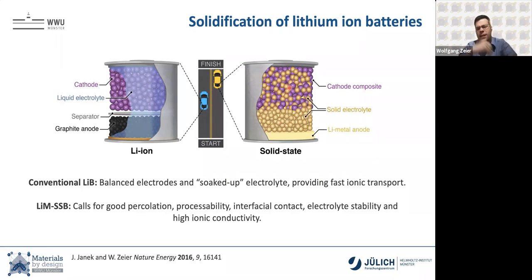So you have grain-grain contacts you need to take care of, you need to be able to process these materials. You really need good interfacial contact, because if there's a lot of porosity, you're going to have a large problem. You need electrolyte stability. Like these ionic conductors, even though they're ceramics in many senses, they're not stones, so they decompose at certain potentials, and you need a high ionic conductivity.